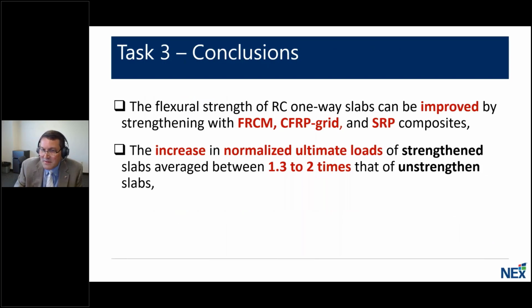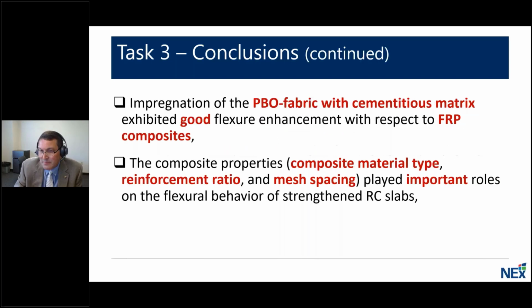Again, for all these one-way slab systems, they can be improved by using FRCM, CFRP grid, and also SRP composites. And the increase in normalized ultimate loads of the strengthened slab averaged between 1.3 to 2 times that of the unstrengthened slabs. The impregnation of the PBO fabric with cementitious matrix exhibited good flexural behavior with respect to FRP composites, and the composite properties, the composite material type, reinforcement ratios, and mesh spacing all played an important role in the flexural behavior of strengthened systems for these RC slabs.